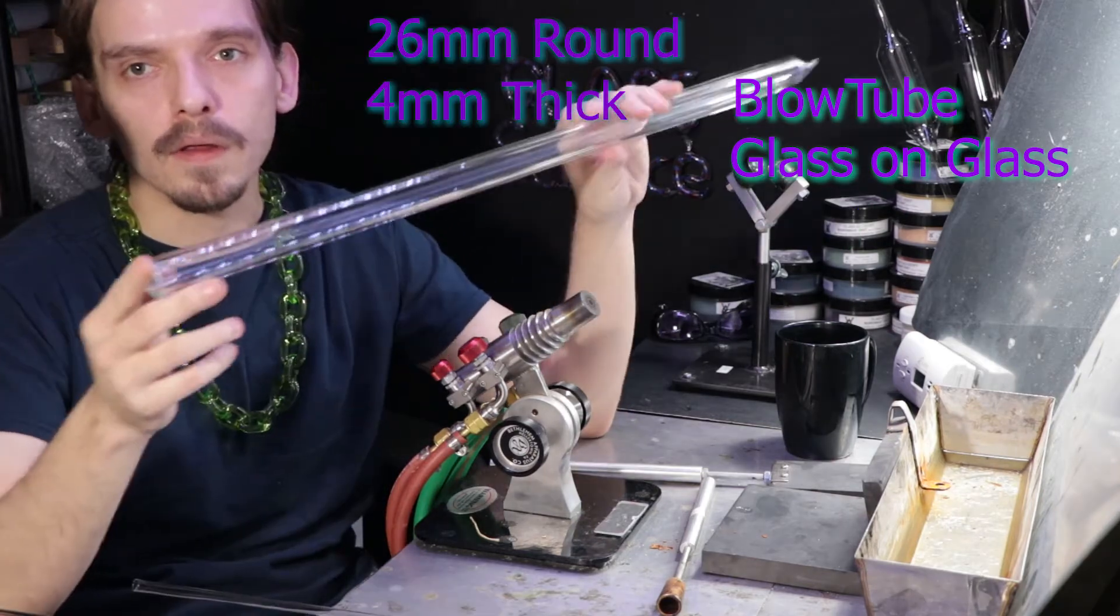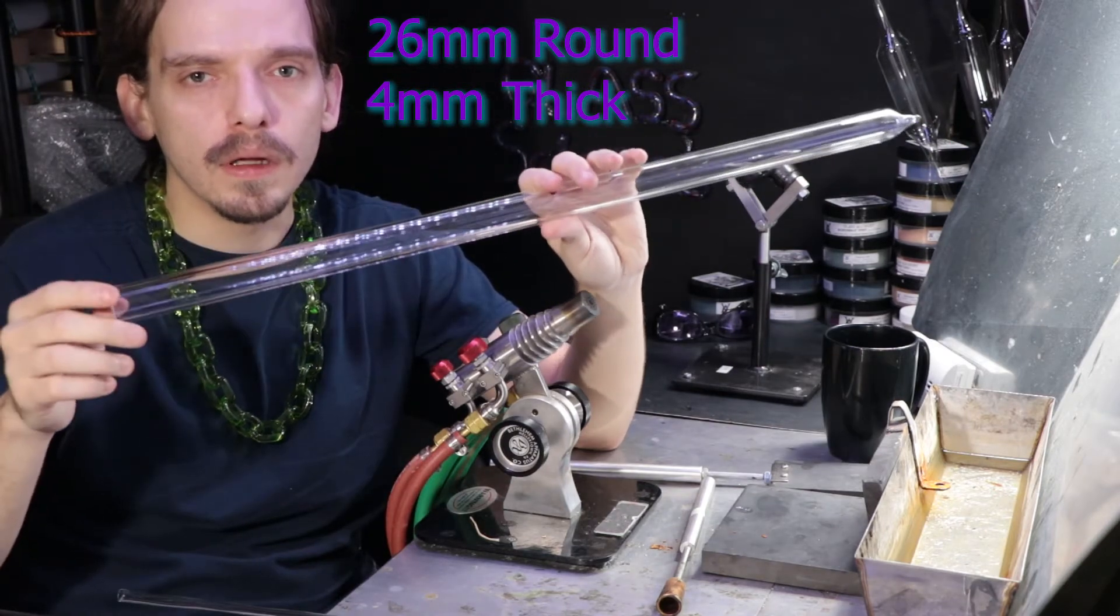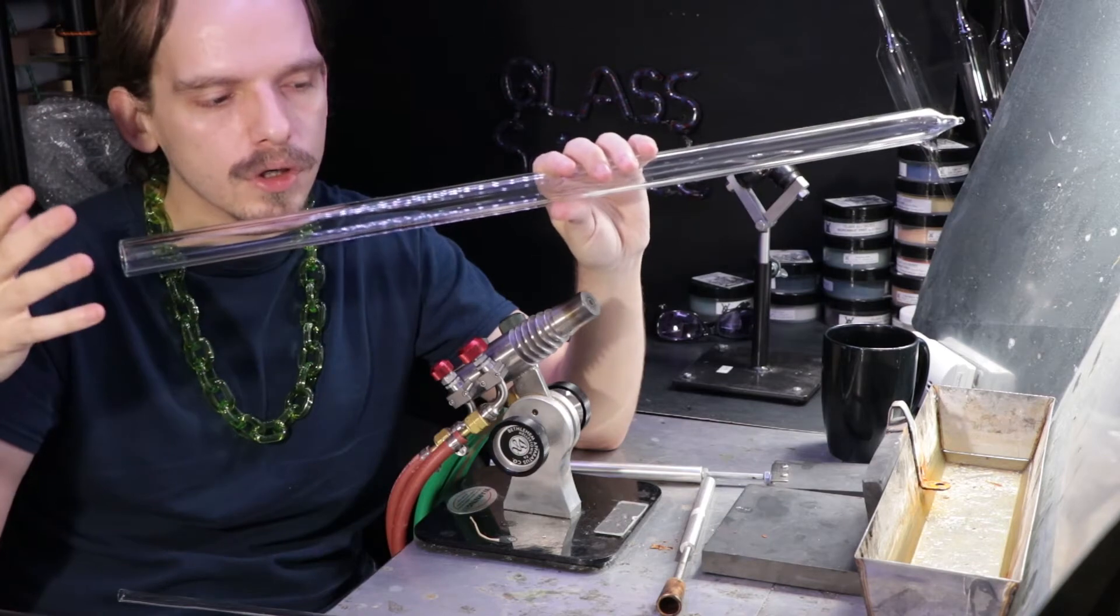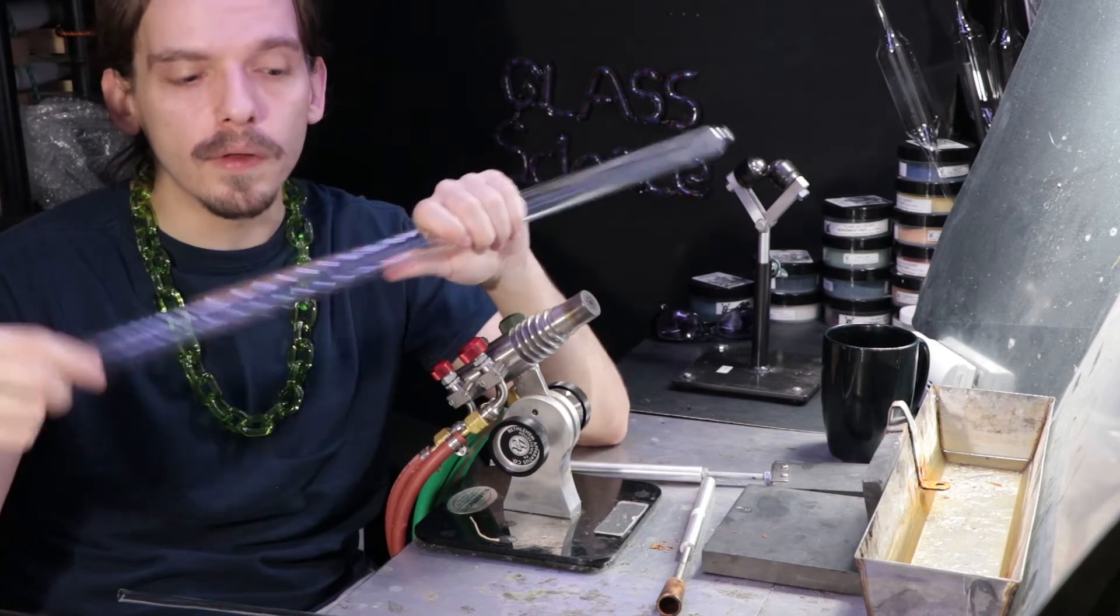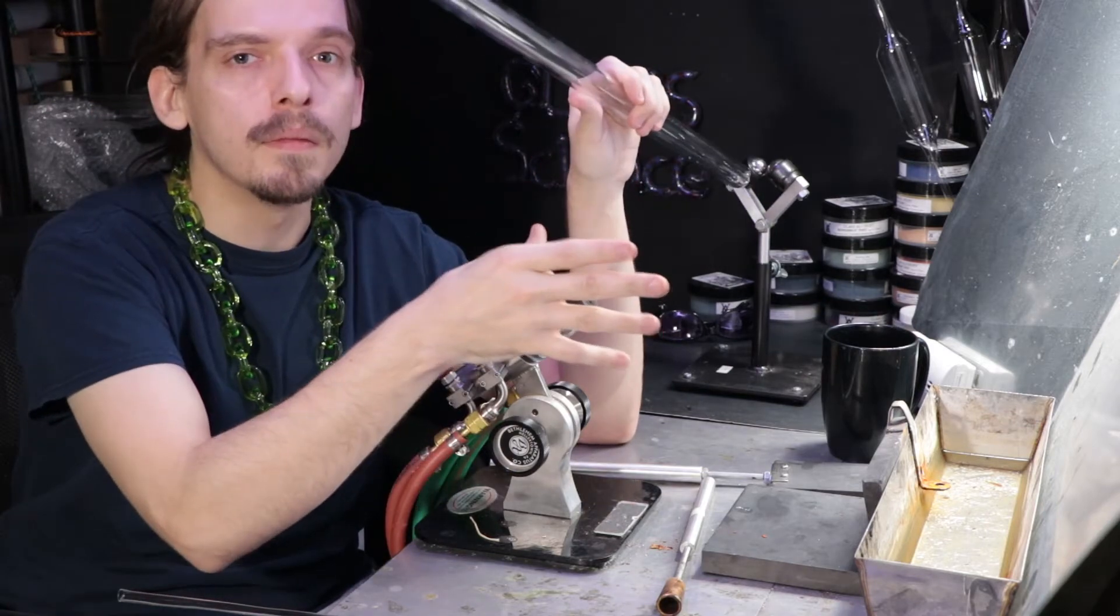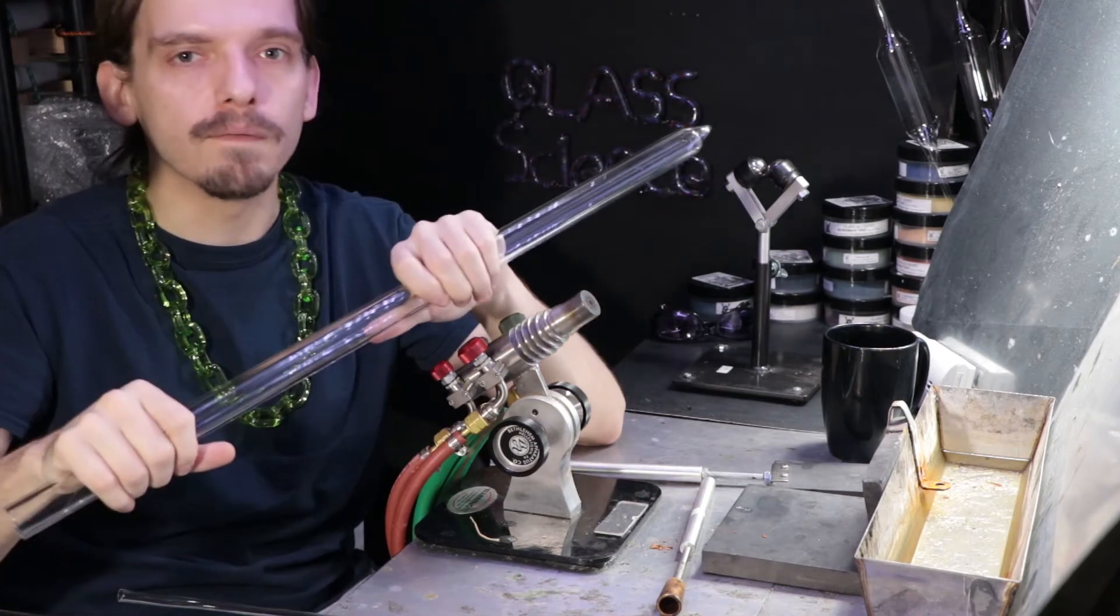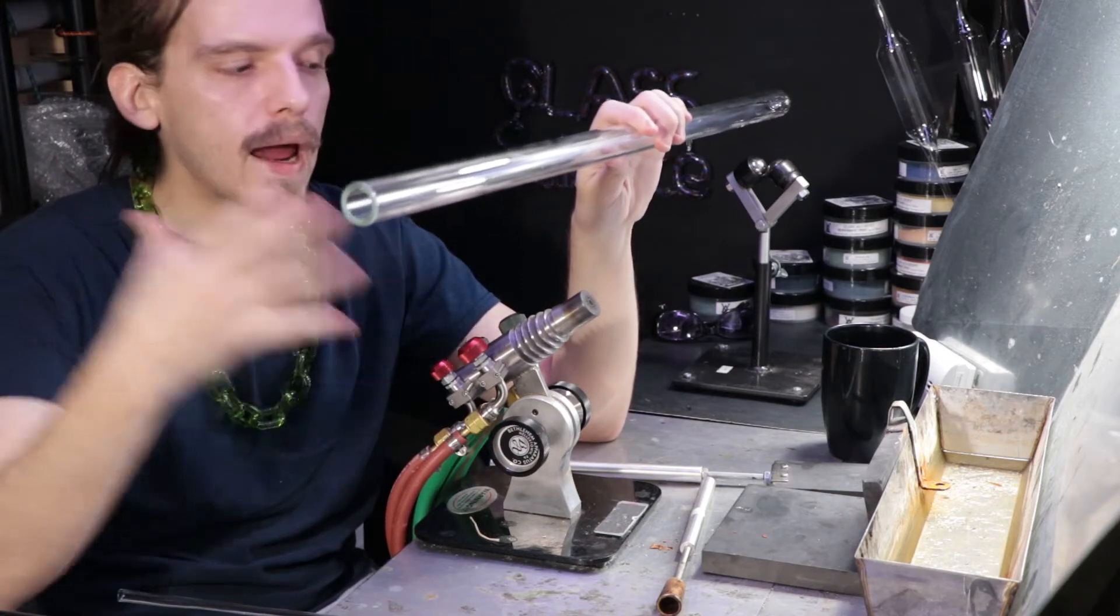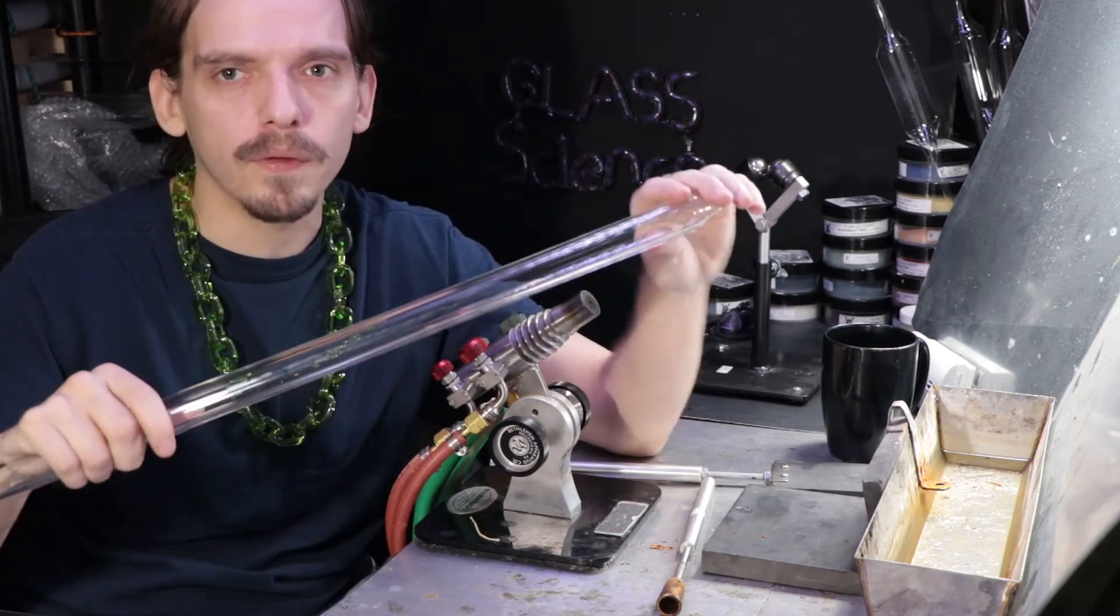This is 26 millimeter, a four millimeter heavy wall. For the American glass blowing we do use the heavy wall usually just because you can blow out the bubbles a lot larger. I just find it's a little bit easier to work on. You'd kind of think starting out you might want to do the standard, the one millimeter thin glass, but it reacts so quickly in the flame that if you're not rotating it right, it's going to end up just getting very lopsided. Whereas this, you'll soak in a lot of heat for a while before you get the reactions from gravity and everything else.